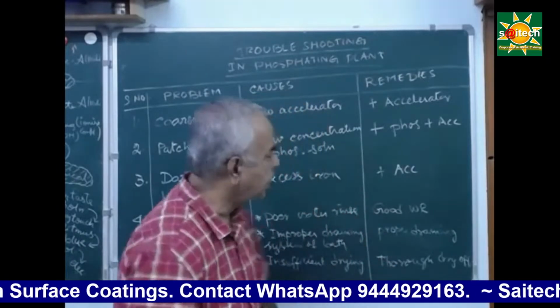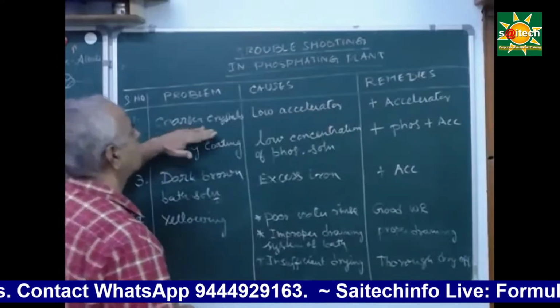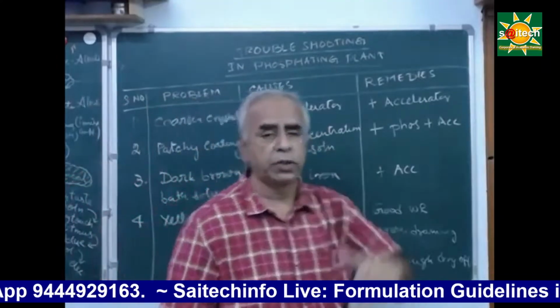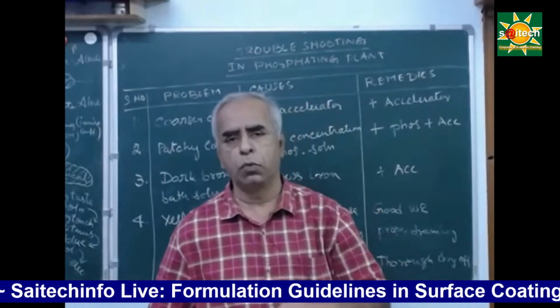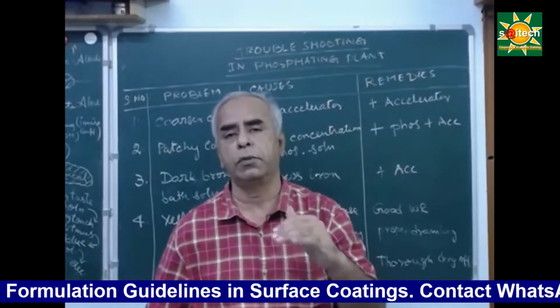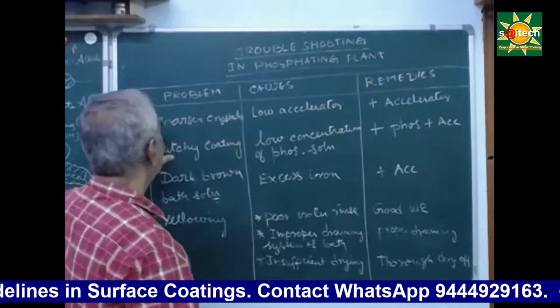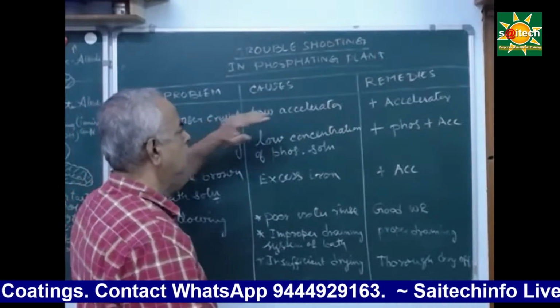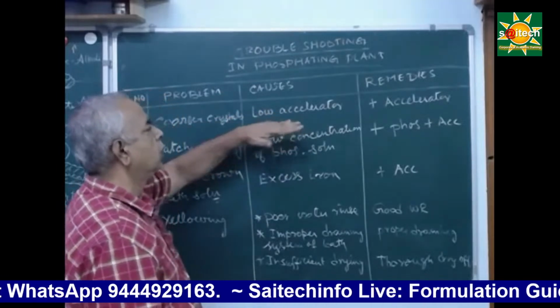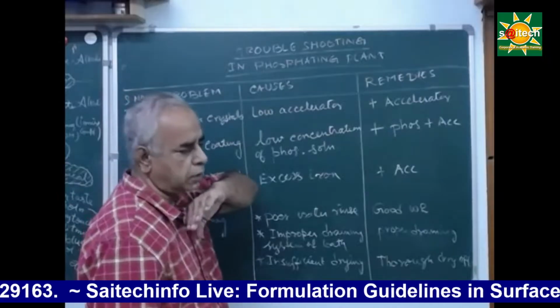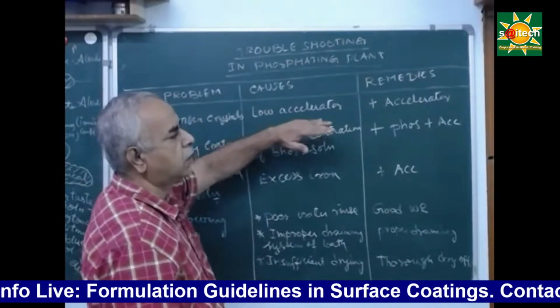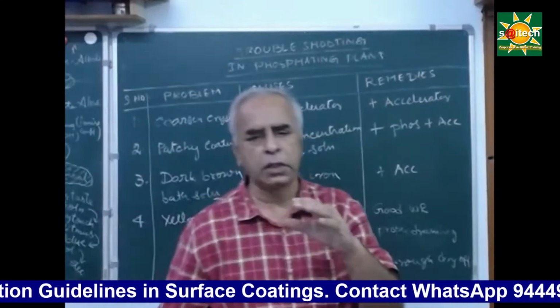So the best thing is if you find such coarse crystals, and not only that, it will affect your salt spray resistance, water resistance, and other dry film properties. So that is why if you find any coarse crystals, normally it is because of insufficiency of accelerator. What is the accelerator? Accelerator is an oxidizing agent.